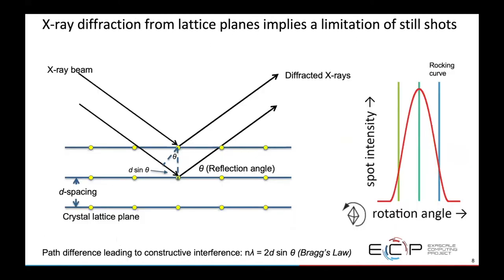I'll show why the traditional terascale procedure fails and we're moving to exascale. This is what you know from a physics class about X-ray diffraction from planes of atoms in a crystal. Due to Bragg's law you get a reflection at a specific angle, but what we've known for a hundred years or so is that it's not a delta function. There's actually a width to the observation of a Bragg spot. If you're rotating the crystal, the Bragg spot flashes on and then it goes off slowly with a certain angular width. This is called the rocking curve, and we don't really know the shape of this function. It's a parameter due to the underlying mosaic disorder of the crystal.